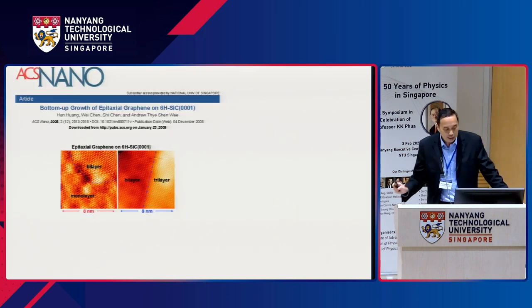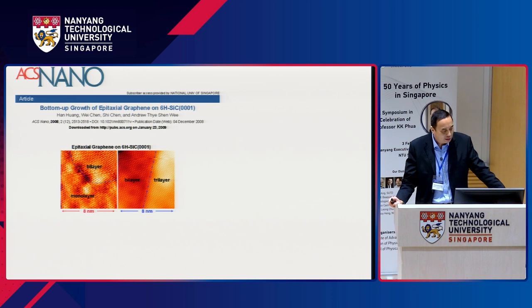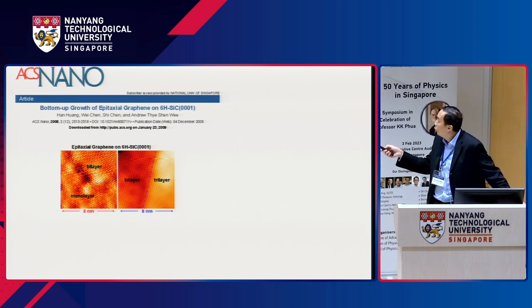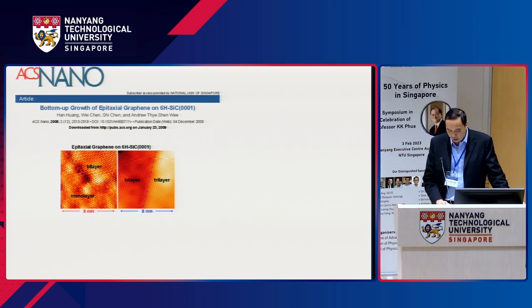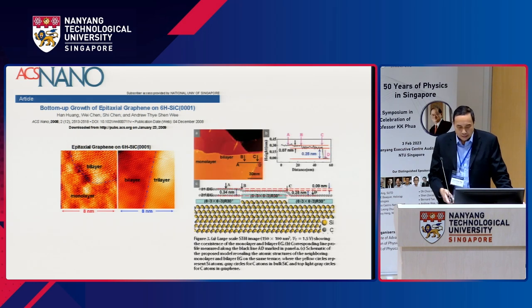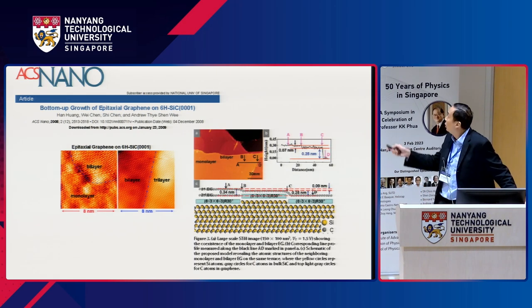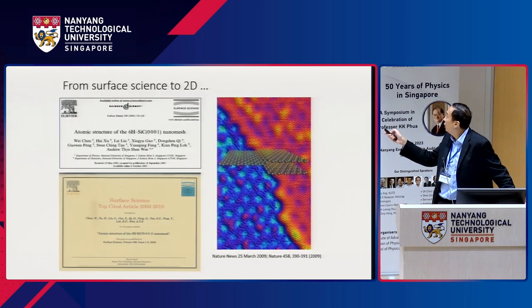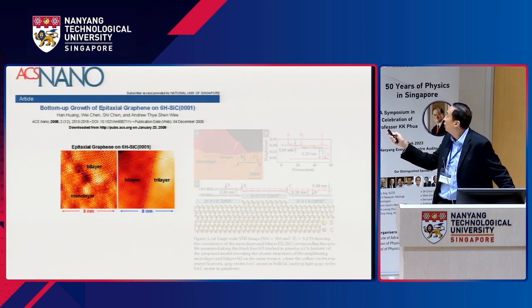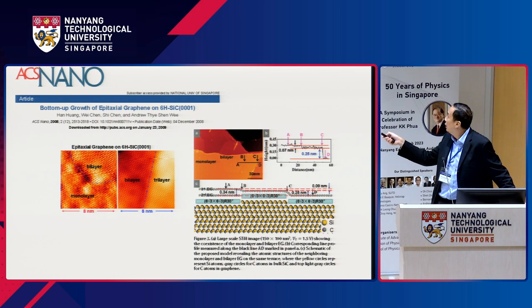So this is a paper that elaborated on the growth mechanism where we had monolayer, bilayer graphene. You can see the top layer is continuous, bilayer, trilayer, the top layer is continuous as well. And we constructed a model. We do have a 6√3 by 6√3 interface, followed by the bilayer and monolayer graphene, and it grows layer by layer.